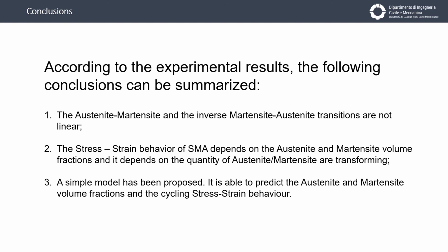In conclusions, in this work we investigated the cycling behavior of a shape memory alloy characterized by a pseudoelastic effect, both in terms of microstructure and in stress-strain behavior at 1, 10, 50 and 100 cycles. From the experimental results, we can see that the austenite-martensite transformation in loading conditions and the inverse martensite-austenite transformation in unloading conditions are not linear. Then, the stress-strain behavior is influenced not only by the real quantity of austenite and martensite, but also by the quantity of austenite and martensite which are transforming, because the transforming phase doesn't participate to the increase or decrease of stresses, but uses the energy for the microstructural transformations.